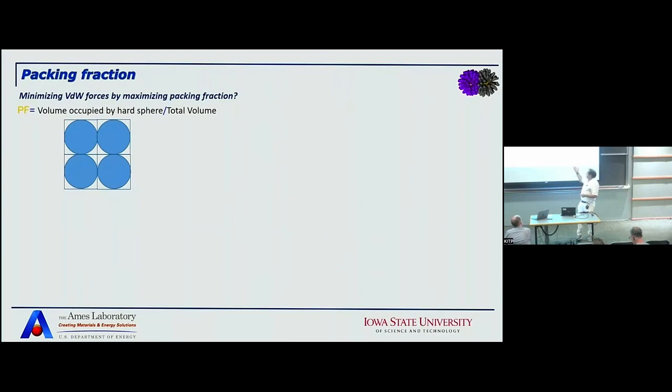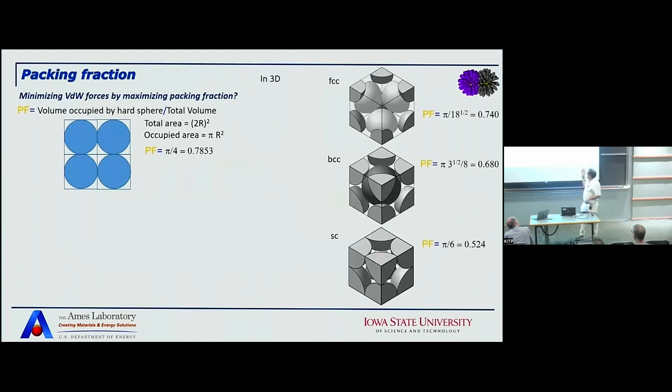For example, for a simple case like this, for a geometry like this, you will have a total area which is (2R)², and then the actual occupied area will be just the circle. Then you get a packing fraction which is this number. If you go to three dimensions, well, there are these Bravais lattices. The FCC gives 74%, the BCC 68%, and the simple cubic is basically half of the space